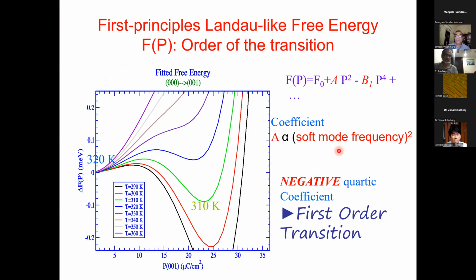And what we show conclusively is that it's the quartic term of the Landau free energy function, this coefficient, which is negative, and that causes the first order phase transition. Otherwise, in the standard Landau theory, usually the third order term, if it is allowed by symmetry, is responsible for a first order transition. And that's why in this case, it's actually called a fluctuation driven first order phase transition.